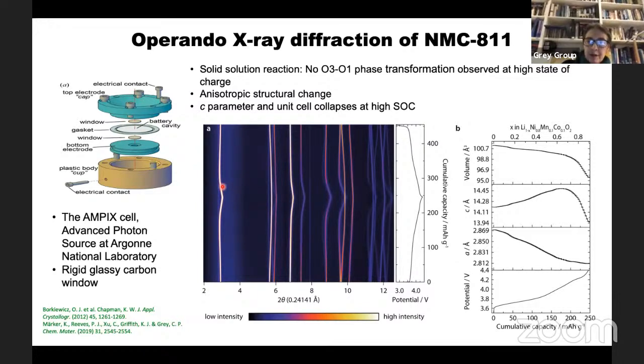This is the diffraction, rather, of NMC 811. So this is the cathode material. Together with colleagues at Argonne National Lab in the US, we've built a cell that allows you to shine X-ray beams through the cell while the battery is cycling. And so what you're watching is a diffraction pattern as you pull lithium out of these materials. This is the so-called 003 peak, which measures the spacing between the layers. And you can watch the layers expand slightly and then collapse. This is shown more clearly here: the expansion and the collapse as a function of how much lithium you remove from the material.